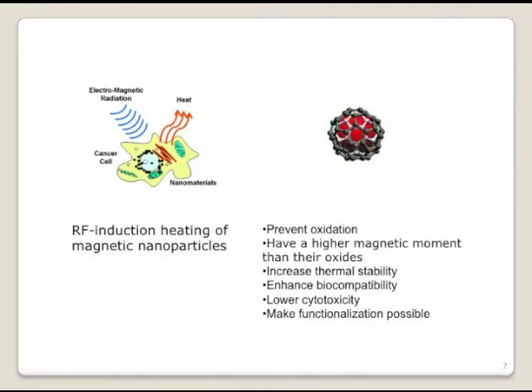We know that nanoparticles are very tiny. They're also very active chemically, so they're unstable in air. So we need to coat them with something to protect them in the metallic state, to prevent oxidation. So the magnetic particle can have a higher magnetic moment than the oxides. Once it's coated with something, it can also increase the thermal stability and enhance the biocompatibility. It can also lower the toxicity. The outside coating also makes functionalization possible. Maybe it can be used for targeted delivery.